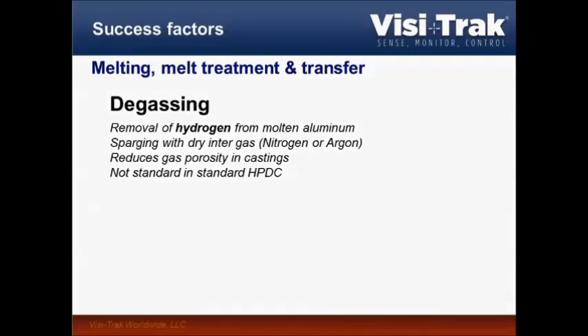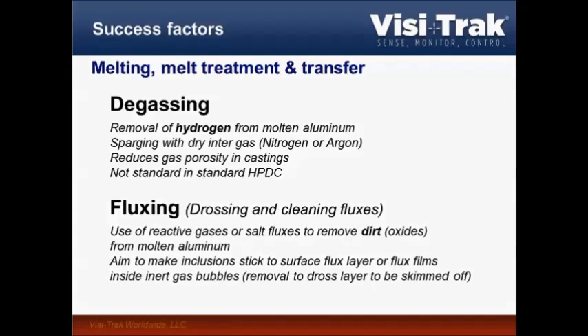If we talk about degassing, that is removal of the hydrogen from molten aluminum, and this is typically done with nitrogen or argon. Ideally, you do want to do rotary degassing, and you could either then inject fluxing directly with the nitrogen or argon, or you do it on the surface. But fluxing here in this case is used to remove the dirt, so the dirt actually sticks either to the bubbles coming up or to the surface.